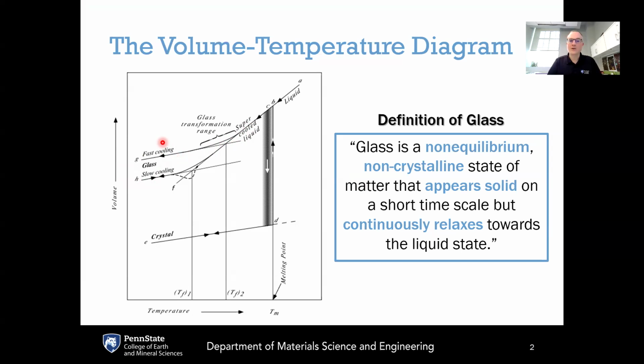And what we learned is that glasses could be made from any liquids provided that you cool them fast enough to avoid crystallization. But this didn't tell us anything about what types of chemistries of the liquid or what types of structures of the liquid would lead to good glass formation versus poor glass formation. All that we learned previously is that some liquids are easier to crystallize compared to others. But now what we need to do in chapter 3 is to dig deeper to understand what is it about the chemistry of certain liquids or the structure of certain liquids that leads to good glass formation versus bad glass formation. Or in other words, what liquids are very easy to suppress crystallization and therefore make good glasses versus liquids that are easy to crystallize and therefore are bad glass formers.